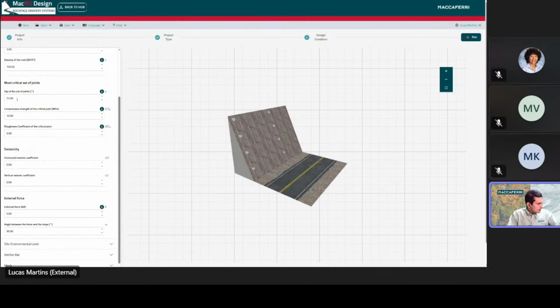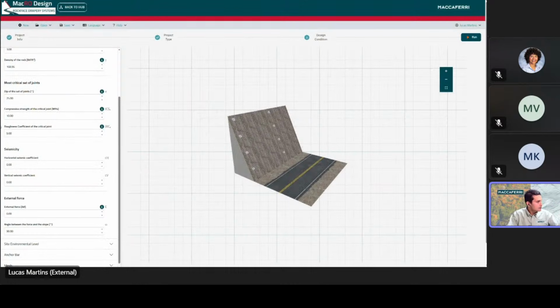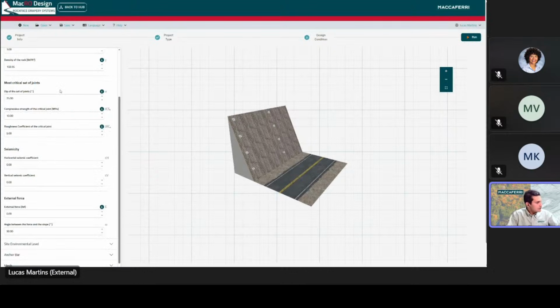Here you have the joint: the dip, compressive strength, and roughness characteristics. Most of the time the information is not present. We would love it to be present. If you want to enter parameters, you can click here for general compressive strength for joints in different types of rocks, or you can leave it at 10.5 as the minimum parameter for that strength. Dip is also a parameter we would love to have, but it's not always present. You can leave it at 25, or 25 to 45 for the most conservative calculations.